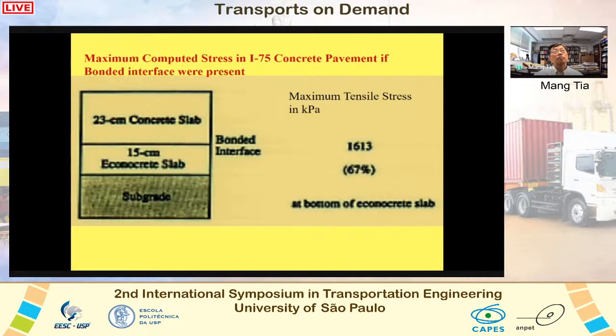If the concrete slab were bonded to the Econocrete layer, the concrete and the Econocrete layer would act as one thick slab, and under the same load and temperature differential, the computed maximum stress would occur at the bottom of the Econocrete layer, and that maximum stress would be equal to only 67% of the flexural strength of the Econocrete. Unfortunately, the concrete slab was not bonded to the Econocrete base in that concrete pavement. If they had been bonded together, this pavement could have much better performance according to our prediction.